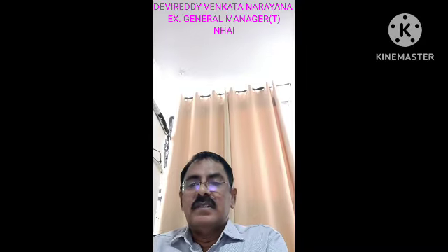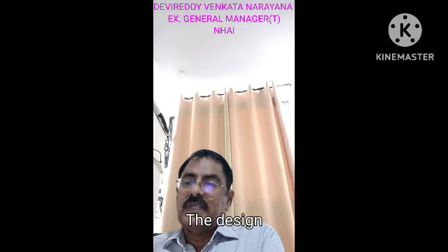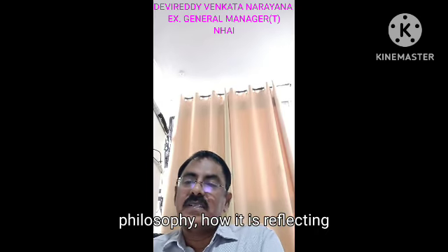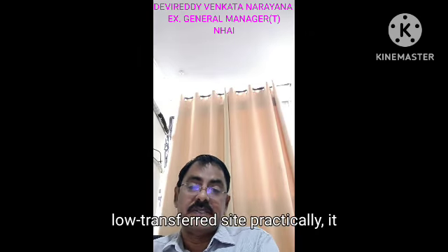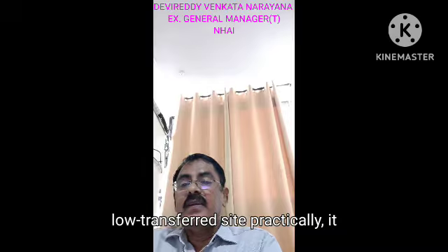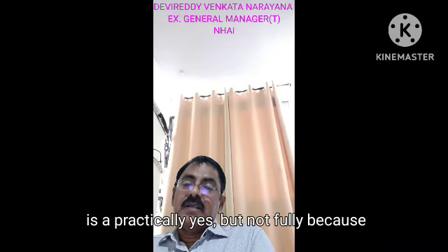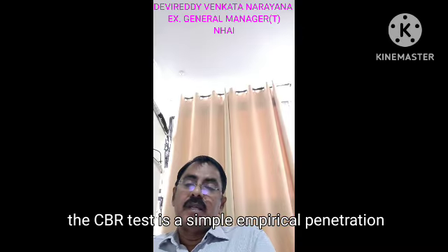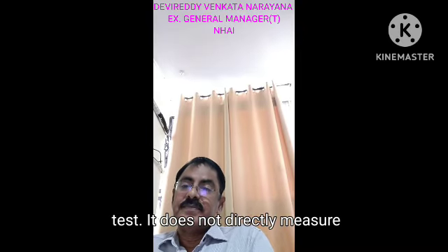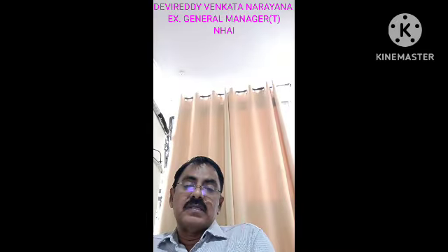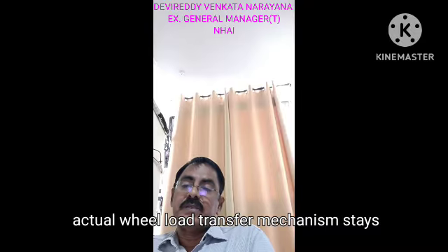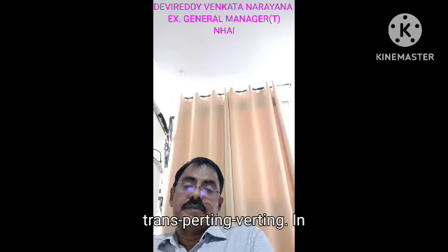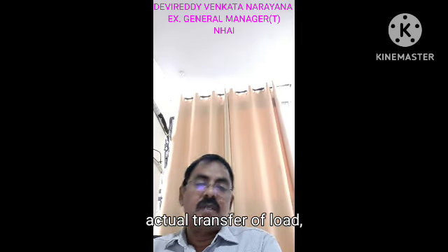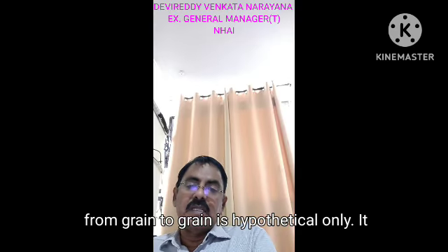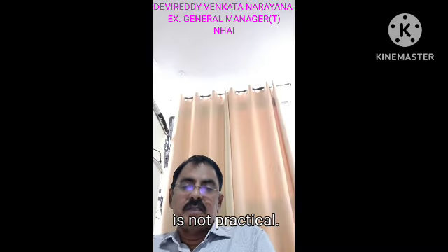Now think about the design philosophy: how is it reflecting actual load transfer at site, practically? So practically yes, but not fully, because the CBR test is a simple empirical penetration test. It does not directly measure actual wheel load transfer mechanism, stress, strains, fatigue, rutting. In actual, transfer of load from grain to grain is hypothetical only. It is not practical.